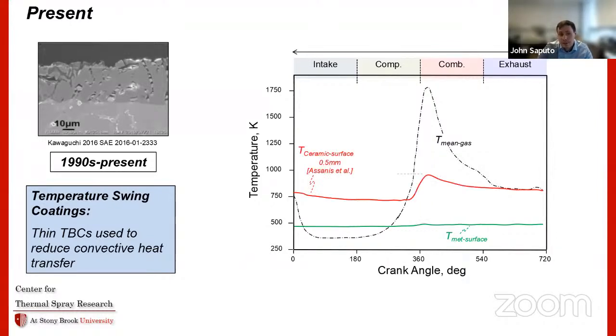So if you put a ceramic, this is a 500 micron thick TBC, in these systems, you see a sort of exaggerated thing happen here. During that intake cycle, the difference between the hot surface and the gas is a lot larger, and this is now smaller. So those heat transfer losses that you're seeing during the intake cycle get even bigger. Ideally, what you'd want in this system is something that looks like this, something that has a low mean temperature, but then quickly spikes up to meet that combustion gas temperature at every point during the cycle.